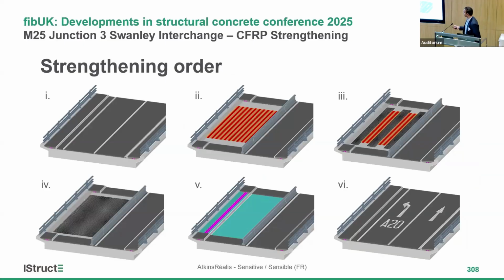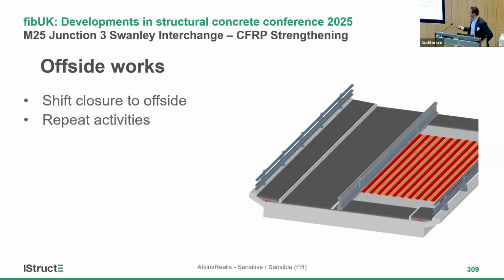Refresher again. Step 1, mark out all the extents, remove the surfacing, check for the plates, remove part of the plates and install the FRP, followed by removing the remaining plates and installing the FRP. Then once it's all set, apply the surfacing and then the markings. So we finished one side, it was open to public, and then we repeat the same procedure on the other side.